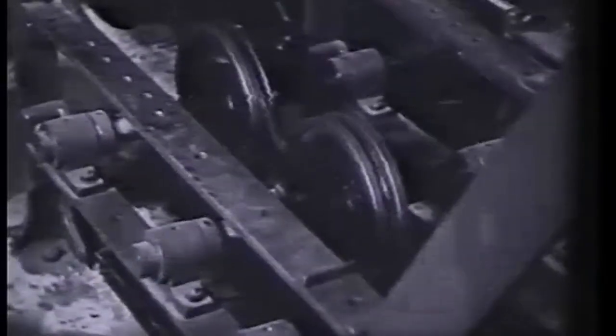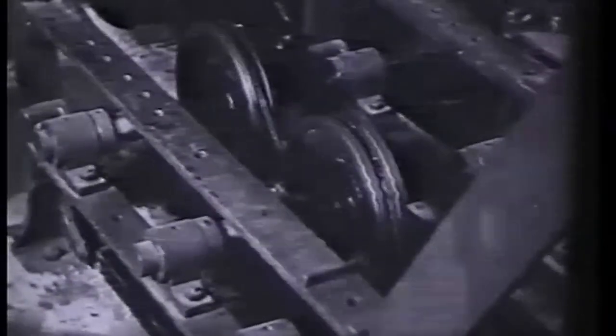A portion of each wire rope is then placed in the tensile testing machine, where strain is gradually applied until the rope breaks. Wire ropes for elevators are subjected to a fatigue test on this machine, where the to and fro movement over very small pulleys causes a breakup, thus providing an accurate forecast of life when applied to its job on an elevator. And here you see the ropes being packed for dispatch throughout the Commonwealth. Especially in the production of haulage and winding ropes for use in mines, the Australian Wire Rope Works Limited have succeeded in making a product equal to the best imported.